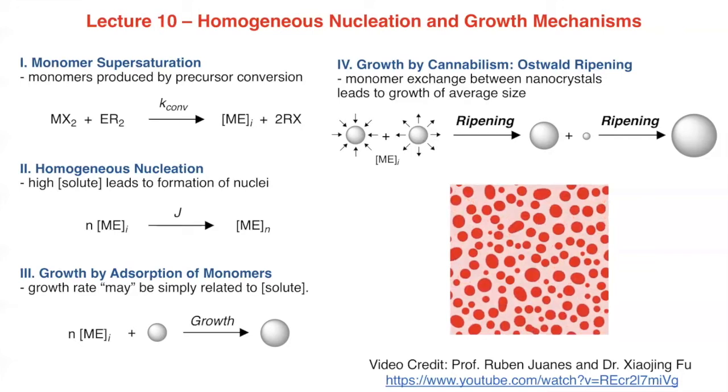So prior to some kind of conversion reaction step that's irreversible, you don't have solute. And solute is formed by that conversion reaction step. And the kinetics of that dictate how fast the crystallization can go. In some cases, it's the rate limiting process, and others it's not rate limiting, but in many cases it will be rate limiting.